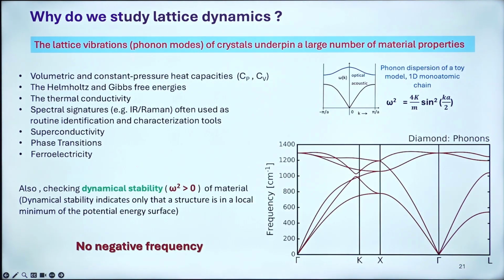Why does one need to understand the phonon dispersion relation or lattice dynamics? This has a direct link with the volumetric and constant pressure heat capacities, the Helmholtz and Gibbs free energies, the thermal conductivity, the spectral signature we can get from IR and Raman modes, and superconductivity, especially the phase transition, which could be temperature or pressure driven, and finally ferroelectricity. This is for diamond, where we get a nice smooth dispersion relation without any imaginary modes.